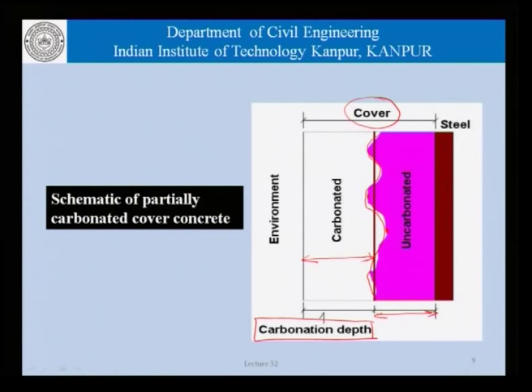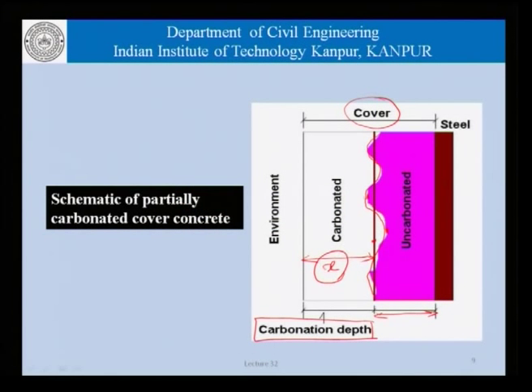Now, this irregular nature of the carbonation front notwithstanding, if we were to draw a straight line as is shown here, then this depth, if it has a value of x, notwithstanding how we measure the x, whether we take it to be the maximum value or the minimum value or the average value, this x is sometimes called the carbonation depth. And naturally, this carbonation depth is a function of time. As more and more time goes by, the carbonation depth increases, and that is something which we need to keep at the back of our mind when we are talking about carbonation in concrete.